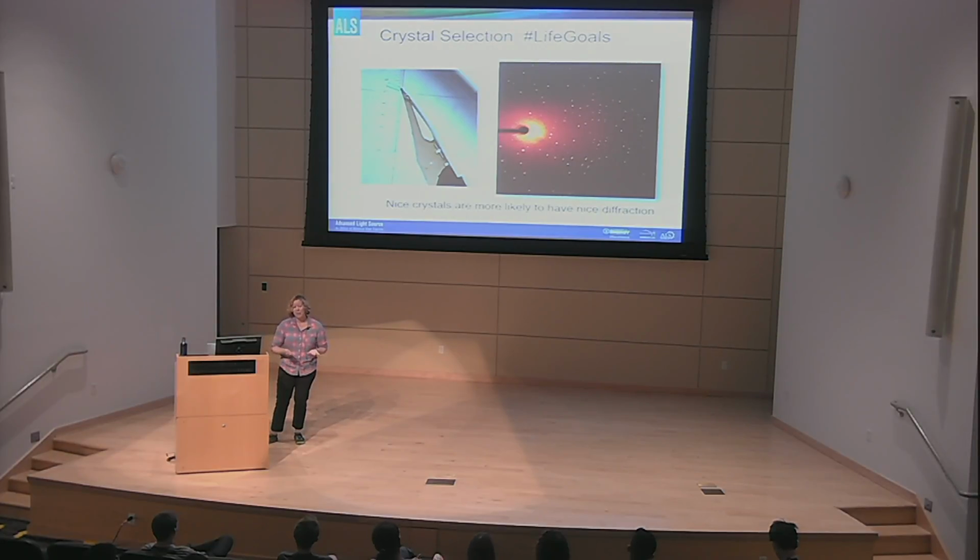So it's still information. Can you do tomography to actually see that or determine the structure? Because, like we said, it becomes 2-dimensional. So once you have more of a continuum effect, you're going to have to be looking at spectroscopies or other techniques that deal in non-Bragg scattering. So maybe SAXS, WAXS, PDF. Those are what you'd have to use if you were getting to a point where it's non-Bragg, it's non-periodic, but you want to know at least nearest neighbor distances or something, then you have to look at the other non-Bragg type techniques. So, yeah. Yes?